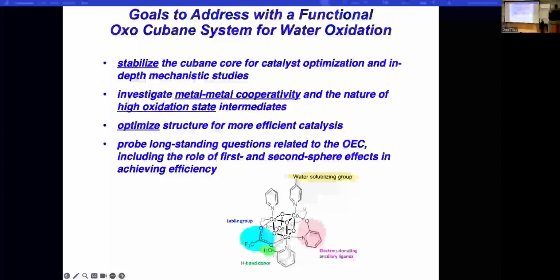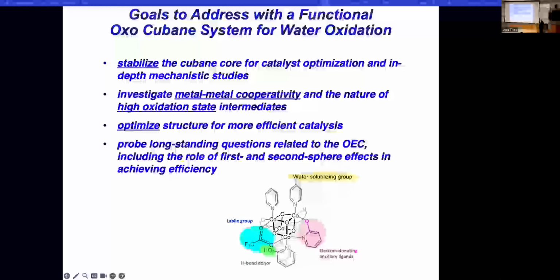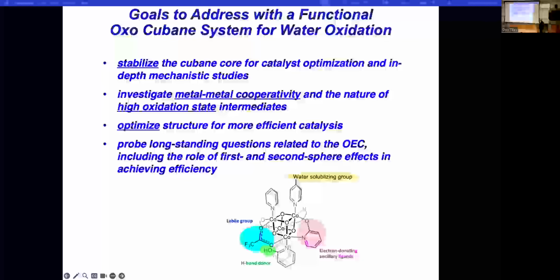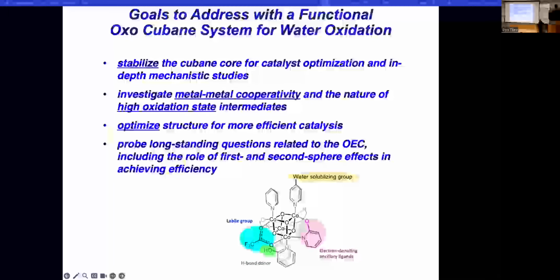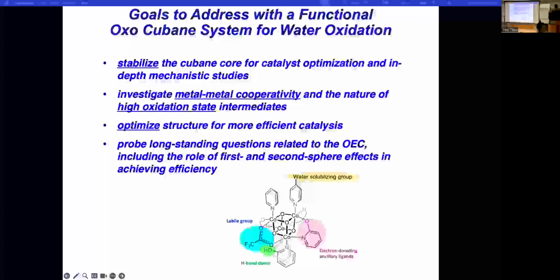Okay, so having a functional system that really does oxygen formation, water splitting, there are several things you want to do with it. One is to stabilize that species against decomposition and agglomeration. I referred to that earlier as a common problem in studying water oxidation. A lot of the papers that describe this chemistry, I think, really involve experiments that make oxides, which are catalysts for this reaction, right? So that's a difficult thing to rule out.